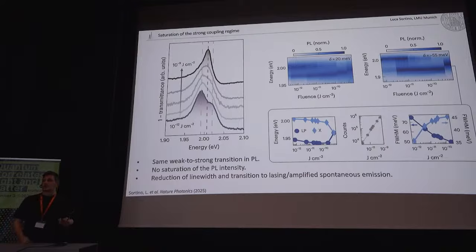But the most interesting part was that basically there was no saturation of the photoluminescence. And this is strange because 2D materials are known to be saturable, basically at certain points through exciton annihilation and other processes. So in this case, we were having an exponential growth. And then there was no option to increase power due to the laser system that was 80 megahertz repetition rate, so we were not even using that much power, and together with that we were not even focusing highly because we were using a low NA objective to capture this light.